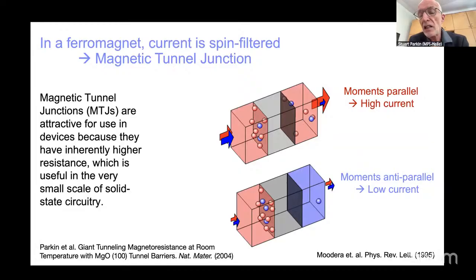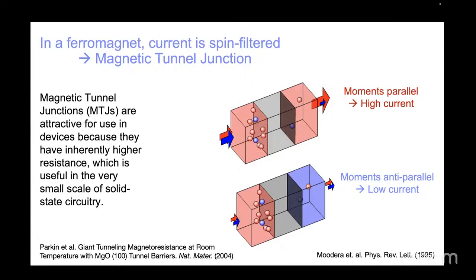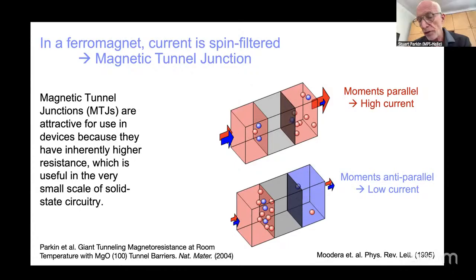In a ferromagnet, when you extract current from the surface, the current is automatically spin polarized according to the density of states of spin up and spin down electrons. When they cross a tunneling barrier, these tunneling electrons have to find empty states with the same spin polarization. So when you have two magnetic layers that are parallel, there are lots of empty states with the same spin polarization, and therefore the tunneling current is high. But when you switch the magnetization, as shown at the bottom, so the two magnetic layers now have opposite magnetizations, the tunneling current is significantly reduced.